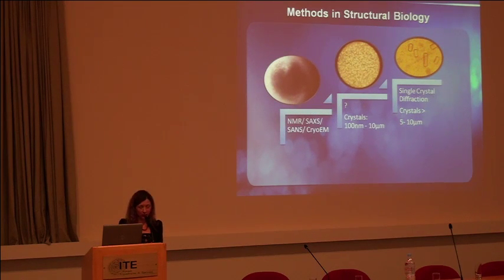Why? Following the previous lecture and the lecture from yesterday, just to remind you that, of course, the most precise picture of a protein structure at the atomic level comes from single crystal crystallography. And you require one single crystal, of high quality, with a certain size. There are crystal size limitations, but now at various synchrotrons this size has decreased, and I believe that even if you have a microcrystal of 5 microns, something in this range, you can still collect good quality data. Proteins crystallize with difficulties, and in some cases proteins are impossible to crystallize.